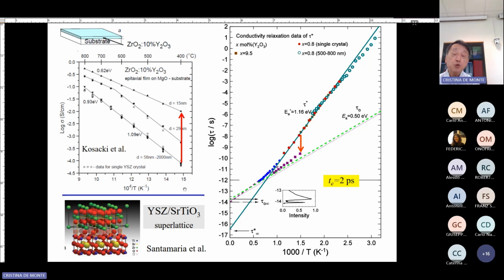And this is temperature. The conductivity, when you make it thinner and smaller, the thickness on a substrate becomes smaller. This is a different thickness. This is almost like bulk. When the thickness becomes very small, in this case 50 nanometers thin on the surface, the conductivity rises, the activation energy changes. It no longer is that much. This activation energy is like the bulk.